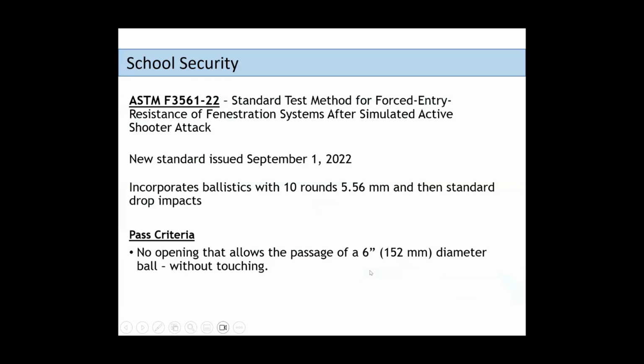Okay, and the last test I want to mention is, in 2022, ASTM came out with a test specifically for school security. Before this, school security testing was just using other tests. There really wasn't much consistency on what test was being used. Basically it incorporates 10 rounds of a 5.56 millimeter gun shooting through the glass. So this is not bullet resistant glass. And then you try to break through the glass with a standard device that tries to penetrate the glass.